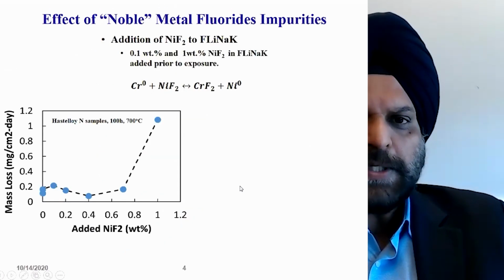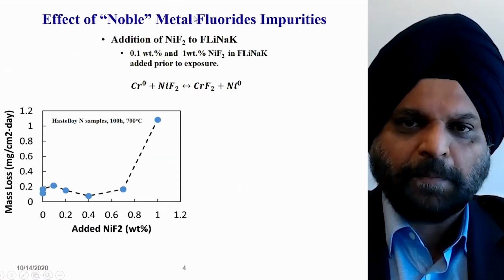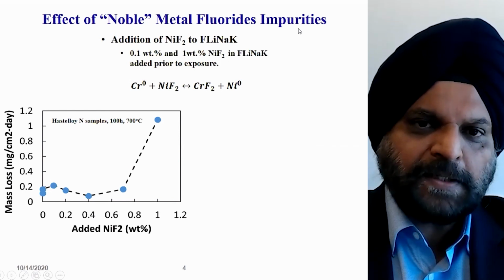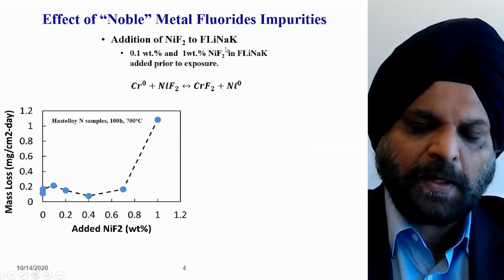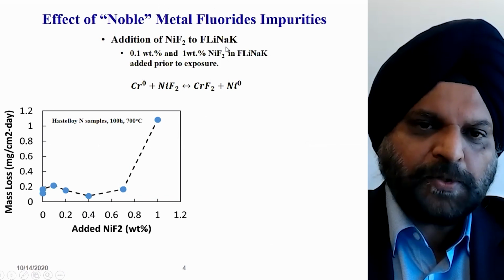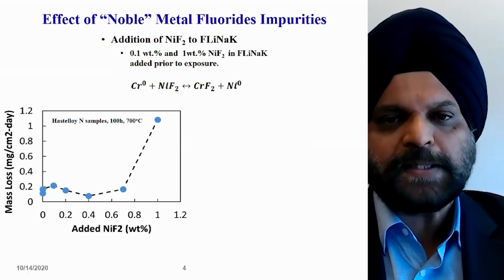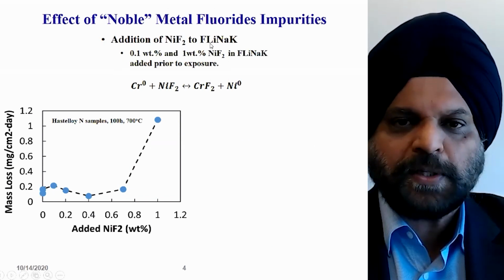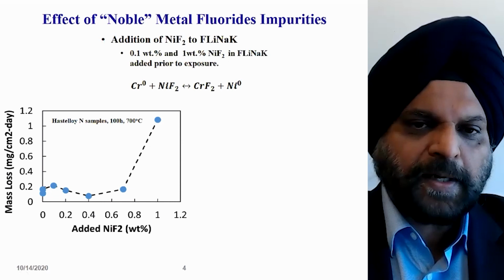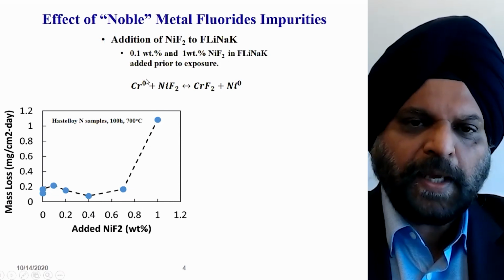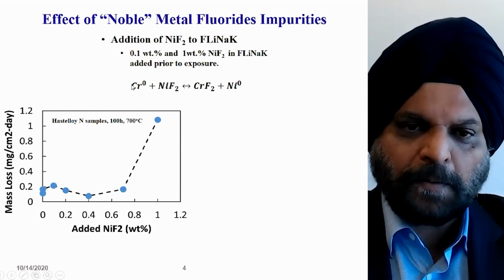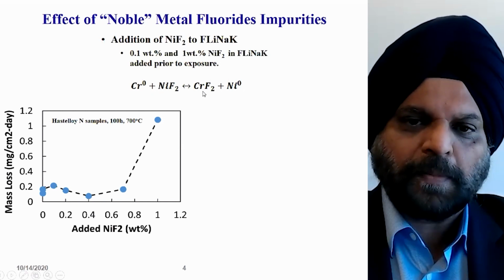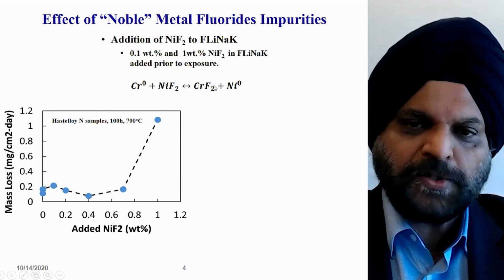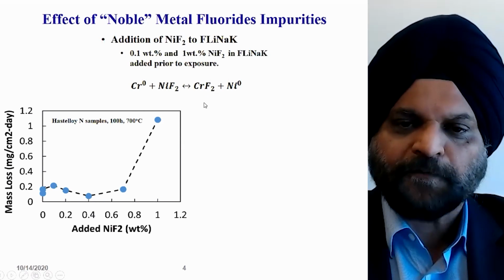So going through these impurities, the first one is metal fluoride. What Kevin did in this case was intentionally add nickel fluoride to FLiNaK, in different compositions, and we found that the presence of nickel fluoride increases corrosion in general, and grain boundary attack in particular. You carry out this reaction where nickel exchanges with chromium, forming chromium fluoride, which is soluble, and leaving nickel on the surface.